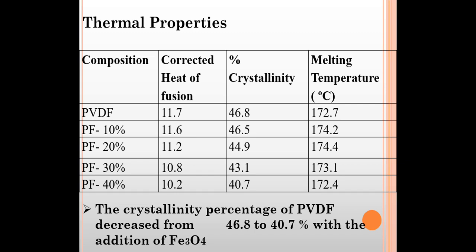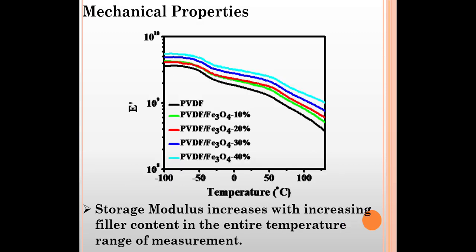This study indicates that the heat of fusion decreases from 11.7 to 10.2 when Fe3O4 nanoparticles are added. This indicates that the percentage crystallinity decreases with the addition of nanofiller, whereas the melting temperature is not affected with the addition of nanofillers. The mechanical properties of the polymer nanocomposites were studied by dynamic mechanical analysis.